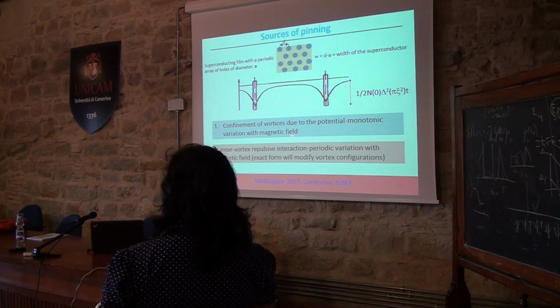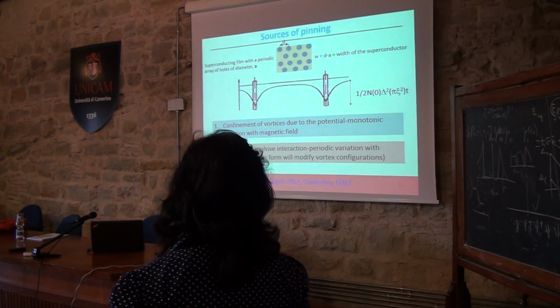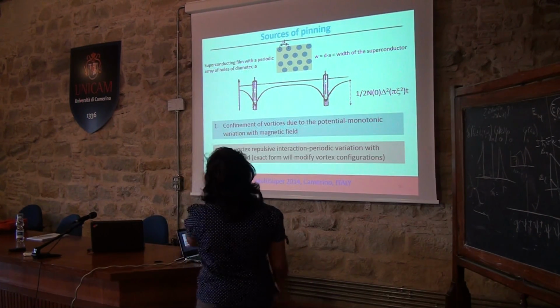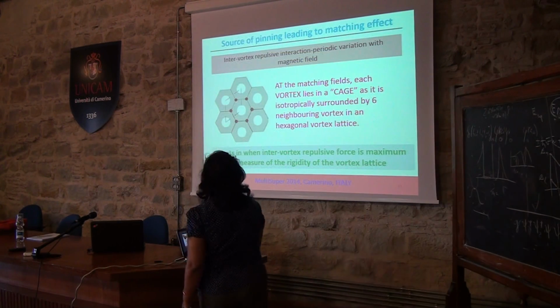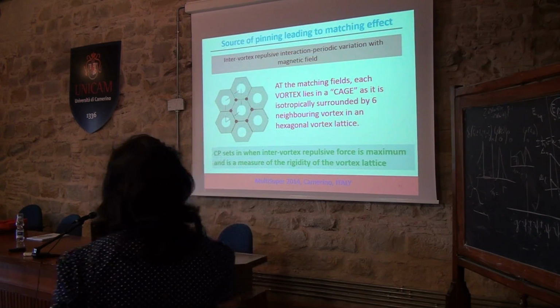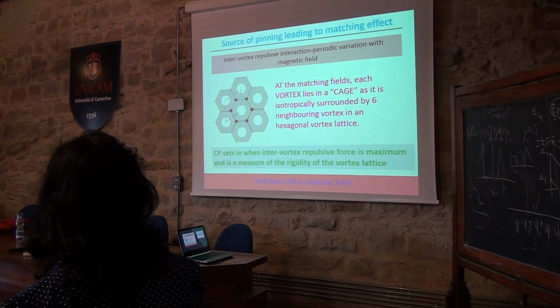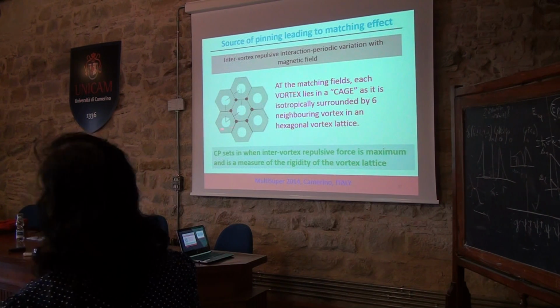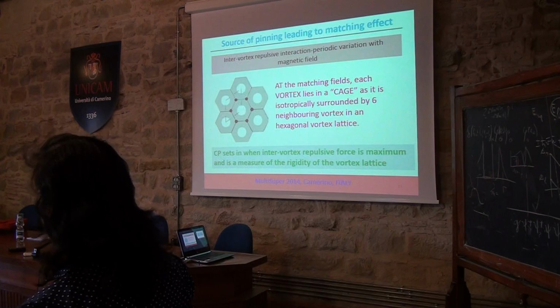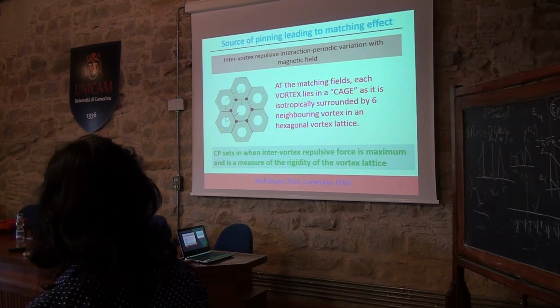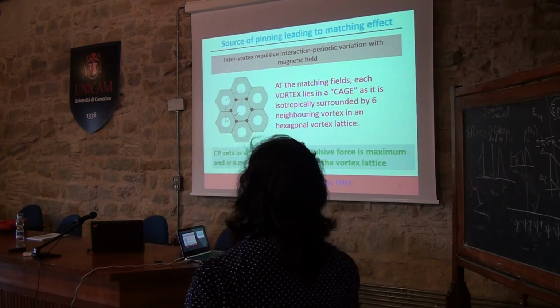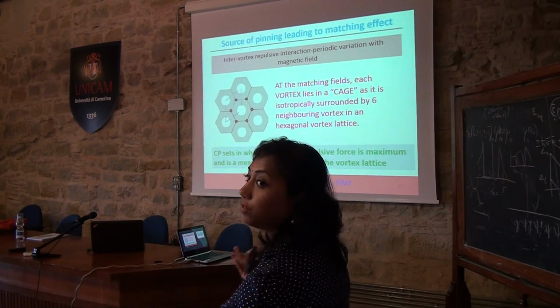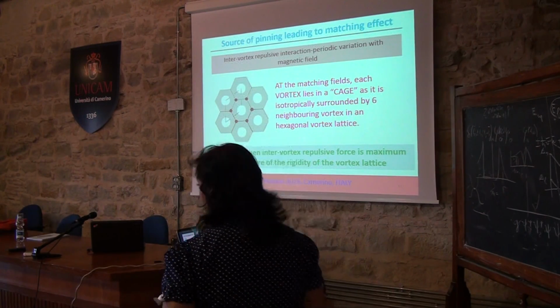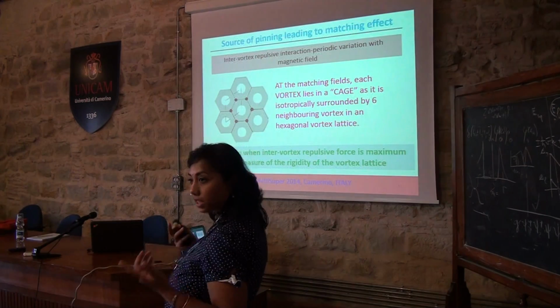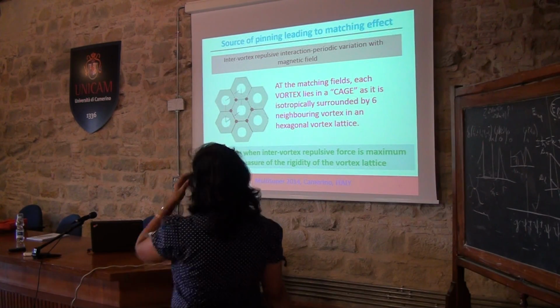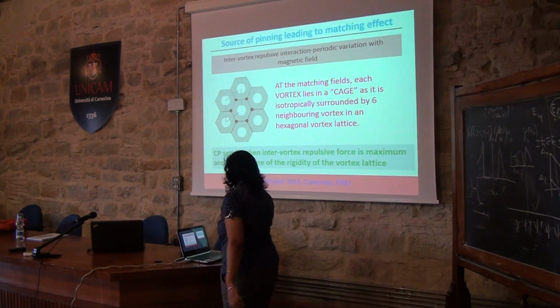However, if we include the intervortex repulsive interaction, then this will lead to the oscillatory behavior. Why does that happen? Because at the matching fields, each vortex will lie in a cage which will be isotropically surrounded by the 6 neighboring vortices, which will happen in a hexagonal lattice, and you will have commensurate pinning such that you will have maximum pinning at these matching fields, and you will have resistance drops.